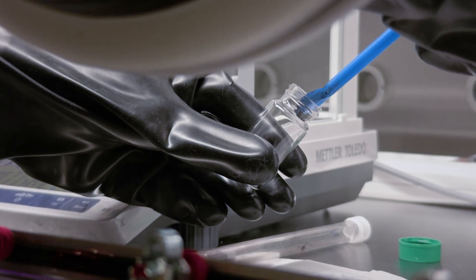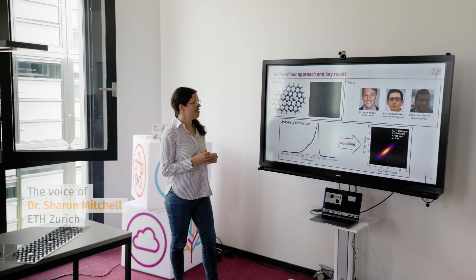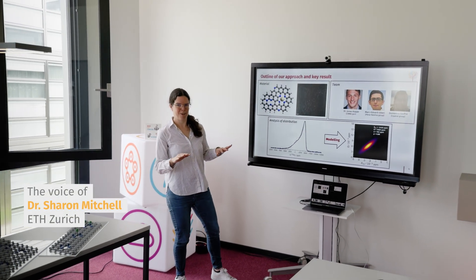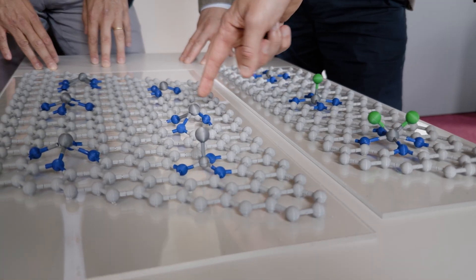the structure is hidden and non-uniform. Electron microscopy can confirm atomic dispersion, but it says nothing about coordination. Traditional spectroscopy approaches are either not sensitive or average all environments into a convoluted signal. So even if we think we've made single atoms, we don't really know how they're bound. Are they coordinated to three or four nitrogens? How are those nitrogens arranged? Do ligands from their synthesis remain attached? This diversity undermines rational design.